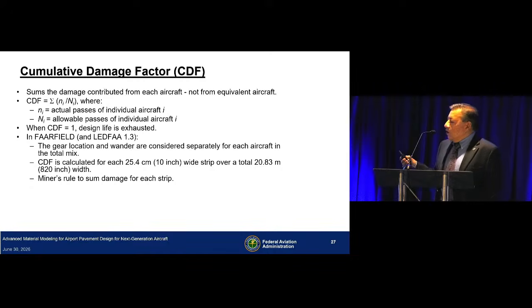So we look at the cumulative damage factor, which is the summation of damage caused by individual aircraft. When your CDF value reaches 1, that means you have utilized the entire life of that pavement structure. In FAARFIELD, the gear location and wander are considered separately for each aircraft in the traffic mix. The pilot tries to put the nose wheel gear on the center line of the runway, but you still see some wander, and that wander depends on what type of aircraft you are in.